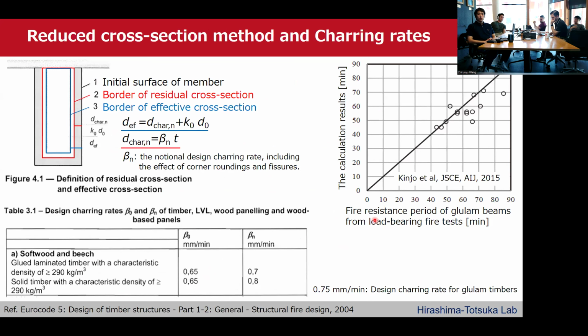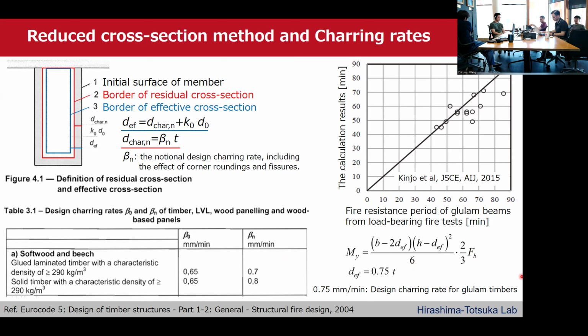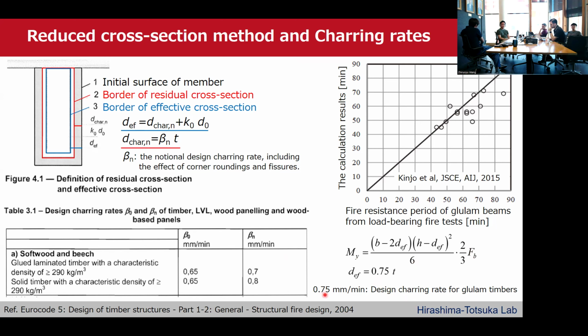So the reduced cross-section method is the most popular method in the design of timber structures. Timber has a low thermal conductivity, so the temperature inside the cross-section of a mass timber element remains low during a fire, and it can be designed using standard structural calculation methods. When using this method, the charring depth or charring rate of the wood must be properly determined. In Japan, the design charring rate is 0.75 millimeter per minute. This value is approximately the same as that given in Eurocode 5 for softwood.